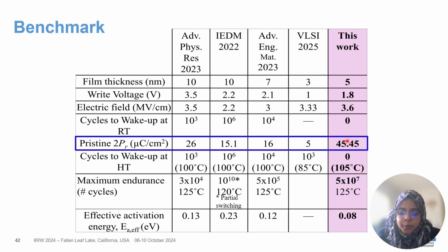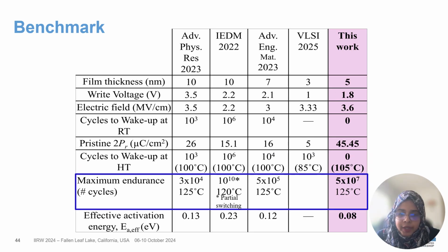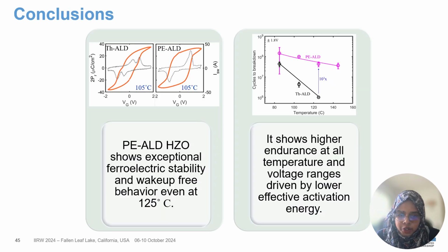We have tried to compare our plasma ALD device with some of the recent reports on ferroelectric capacitors, and we see that we are at a pristine stage. We are getting better polarization compared to others, and we need 0 wake-up cycles at higher temperatures, whereas in other reports we see that at least 10 to the power 3 cycles are necessary at higher temperature. We are also getting better endurance values compared to other reports at full switching condition.